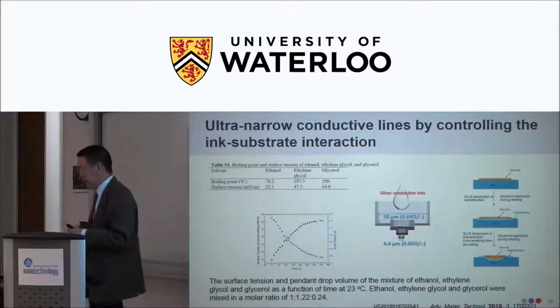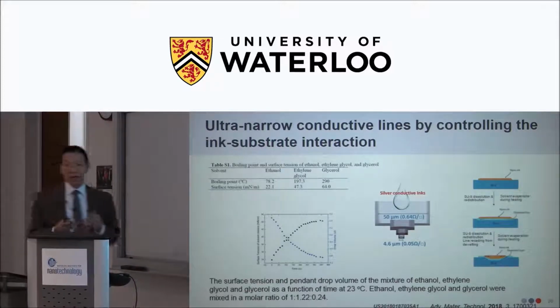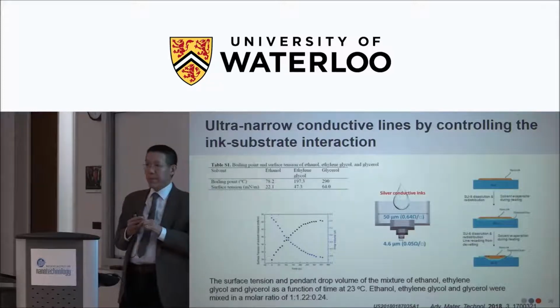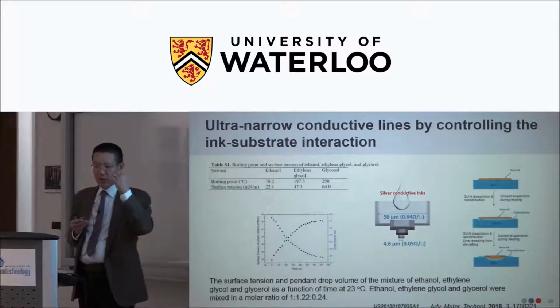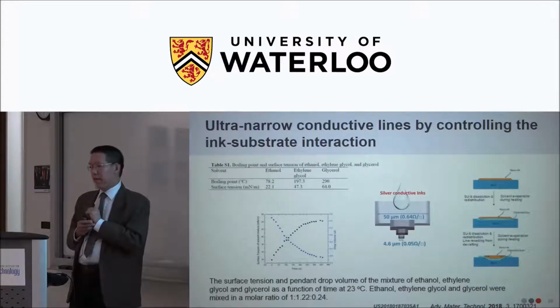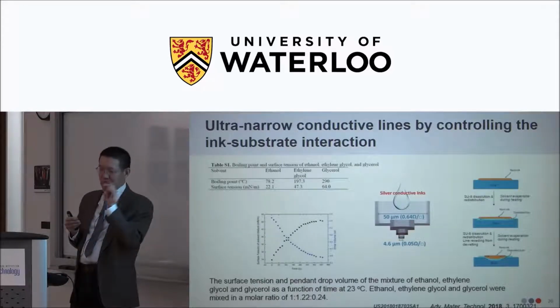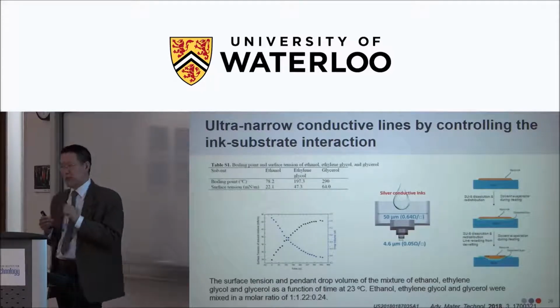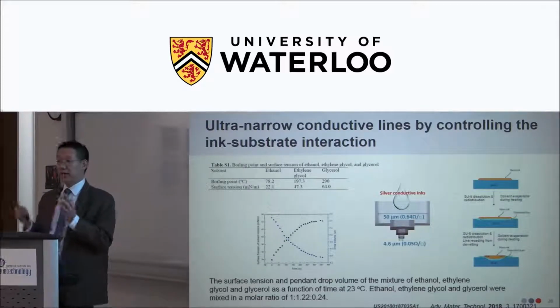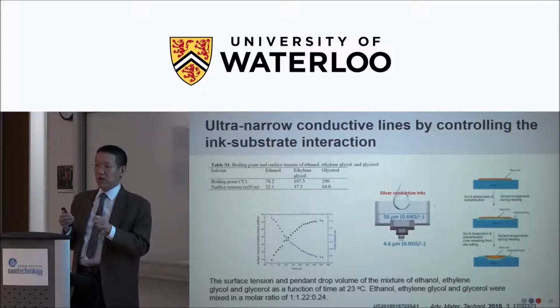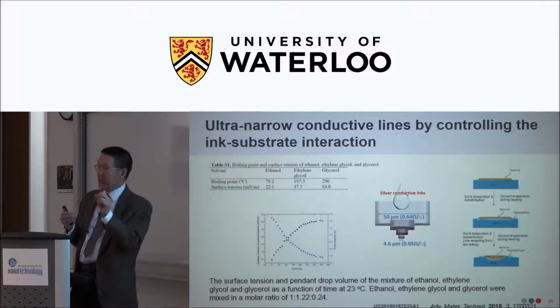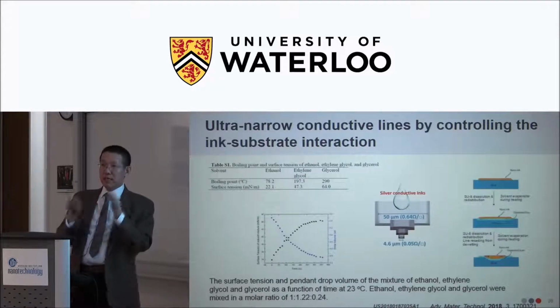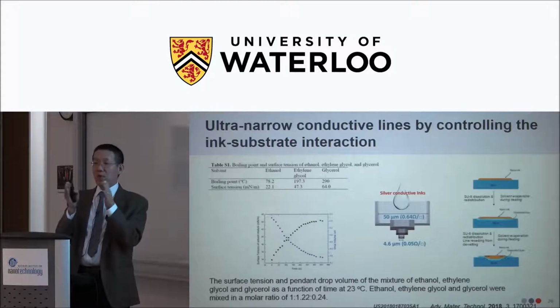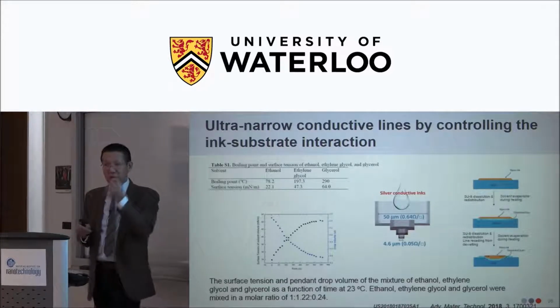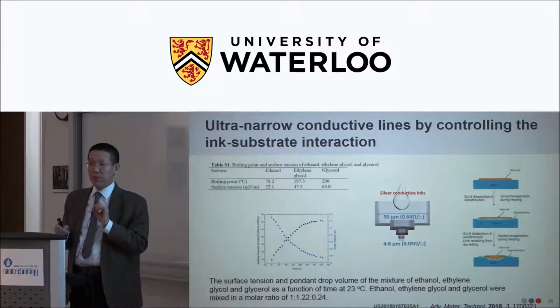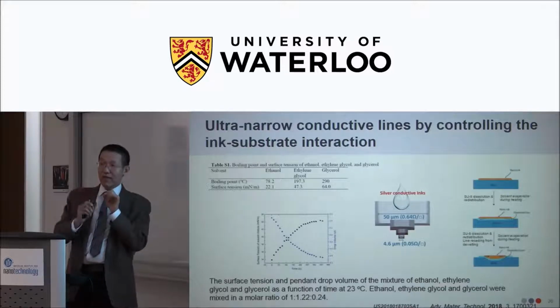Another thing we use the ink-substrate interaction for is to make very narrow lines. As I mentioned before, inkjet printing is one of the few technologies with which you can make a very thin layer. When you use flexo or gravure printing, typical line width will be about 80 micrometers. There's some newly developed reverse offset that can go narrower, but typically they use a very diluted ink. So it can make 1, 2, or 3 micron wide lines, but because they have to use a very diluted ink, the thickness is very low, okay? But the total conductance of a line is very high.